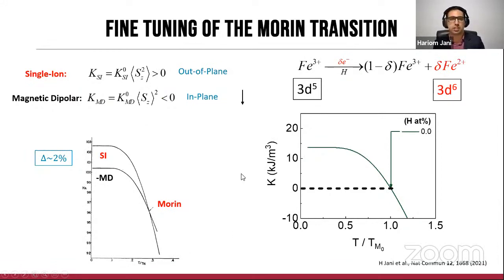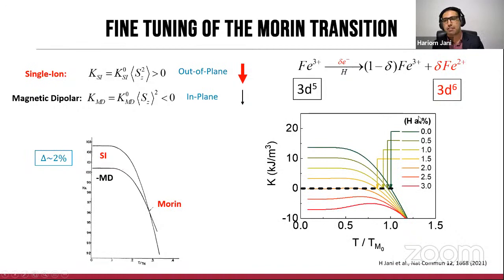For very specific technical reasons, it turns out that this is a negative value, and therefore effectively the single ion suppresses much more of the magnetic dipolar part, and therefore by tuning hydrogen, we're effectively able to go from a positive to negative transition to a completely negative remaining state, which then drives the annihilation of the spin reorientation transition in the system. And because this is reversible, you can go from green to red and red to green again, and so on and so forth.